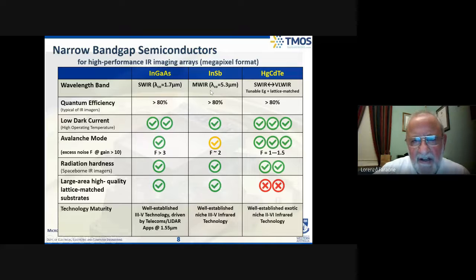Indium antimonide is an excellent infrared detector material, but it has a fixed cutoff wavelength at 5 microns, so it cannot operate in other wavelength bands. So indium gallium arsenide and indium antimonide are basically fixed in the shortwave infrared and the midwave infrared.